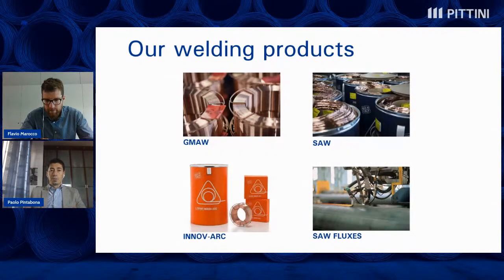And as a first step, the wire rod goes through a double cleaning process at the beginning of Pittarc production. So at the starting point, the mechanical descaling, and then the chemical pickling by sulfuric acid, and then rinsing. The manufacturing process starts from 5.5 millimeter wire rods, and it is reduced to an intermediate diameter by the first drawing machine with dry chemical soaps, which help improve the cleaning and also the drawing speed.